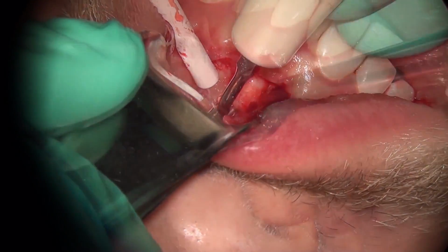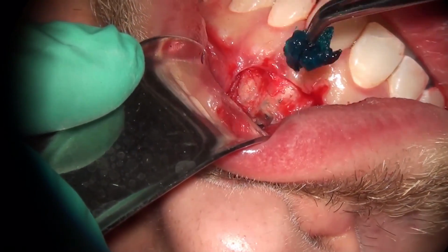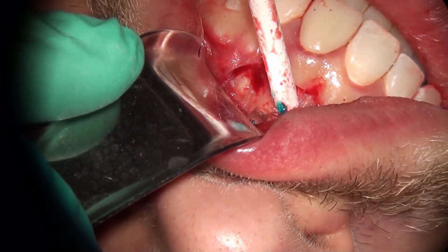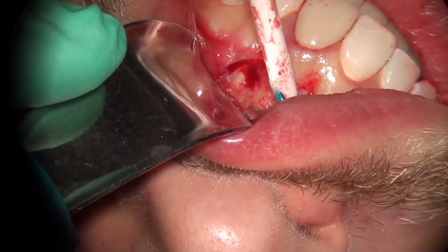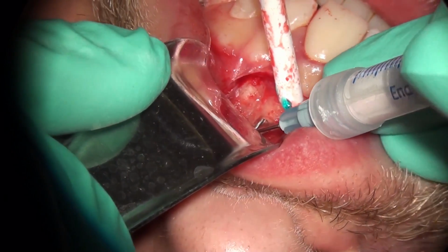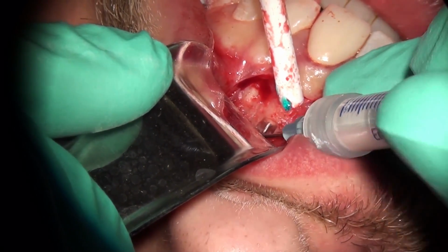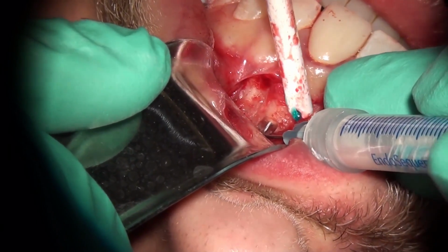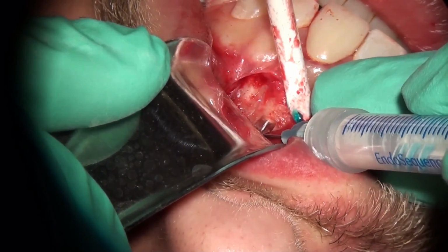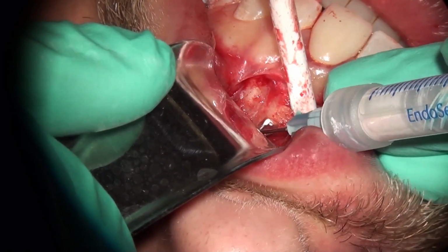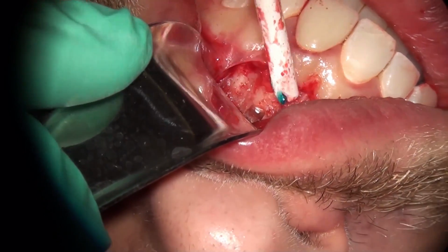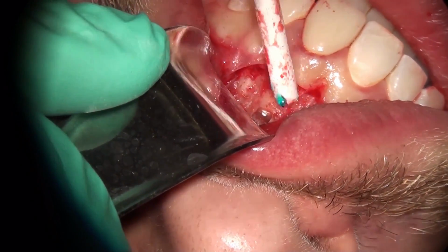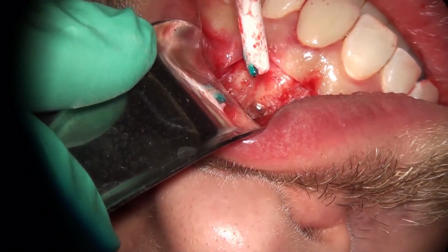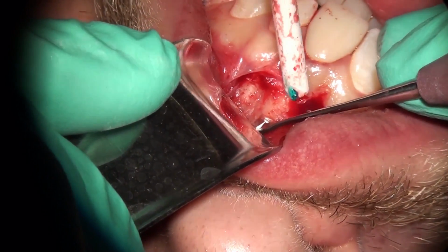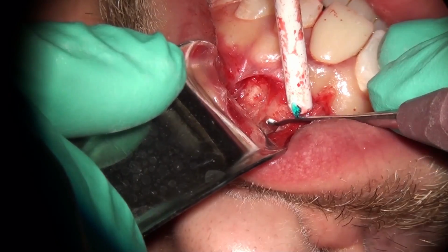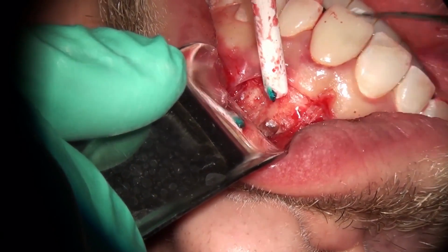So we do a submarginal incision here so we don't have to disturb the area above here, and do the same lid technique now at the apex of the same tooth, using the injectable material to inject into the root and then slowly back out as we're injecting. And then once we have filled all the way to the top, then you can place a little ball. Here in this case, I use the cone of the putty, but you don't have to use a cone. You can just place a little ball of it. It's a little bit faster and it provides less manipulation of the putty.